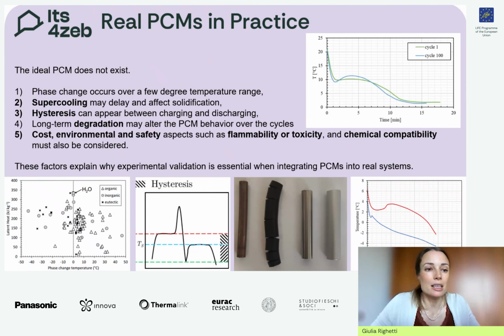We have real PCM. The ideal doesn't exist, for many reasons. First of all, the phase change is not isothermal, but occurs in a temperature range of a few degrees. It could be 3, 5, but also a 10-degree temperature range. Then sometimes we have supercooling. That is a phenomenon that may delay solidification and also alter the solidification temperature range by a lot of degrees, sometimes, unfortunately. Then we have some hysteresis that can appear between charging and discharging, affecting the cycle symmetry.